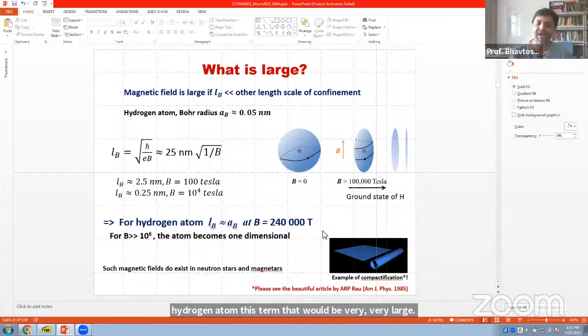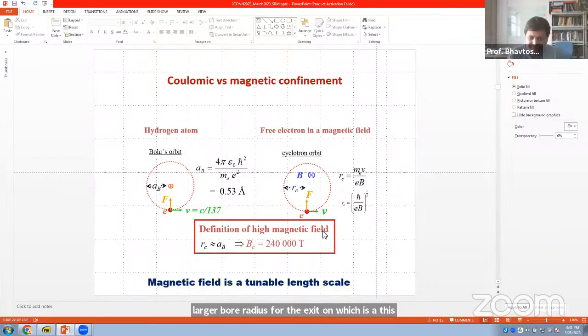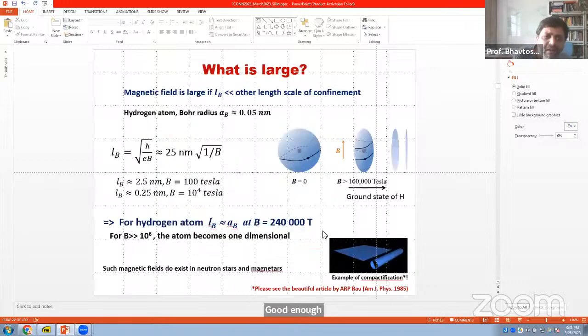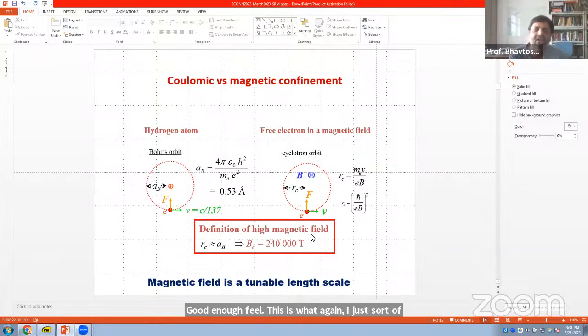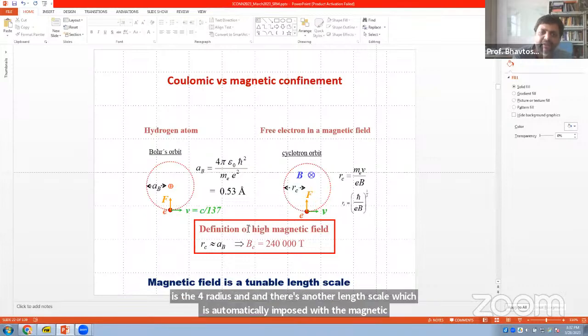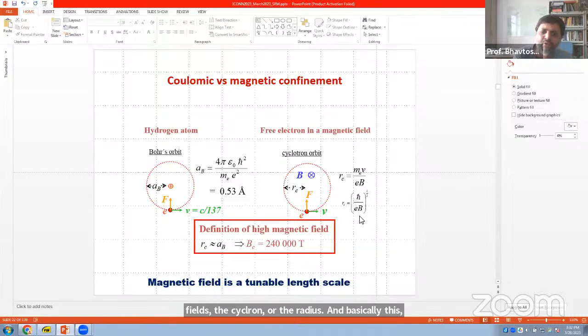But on account of the reduced binding energy and the larger Bohr radius for the exciton, this becomes much, much smaller, and even 10 Tesla turns out to be a good enough field. So again, the hydrogen atom has a certain length scale, the Bohr radius, and there's another length scale automatically imposed with the magnetic field, the cyclotron orbit radius. The cyclotron orbit radius scales as one over the square root of the magnetic field, so you can change the cyclotron radius continuously by increasing the magnetic field.